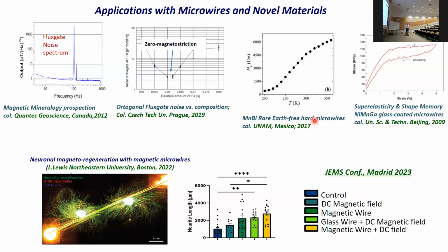So in this, you see this behavior: the coercivity increases with temperature. This is completely unusual. Normally, coercivity decreases with temperature. It is related to the anisotropy of the material. And although the value of coercivity is not very large, what is important is that at high temperature, when neodymium iron boron decreases the coercivity and is no longer so reliable for applications, some other alternative alloys can replace it. This is not particularly the case yet, but this is the trend.